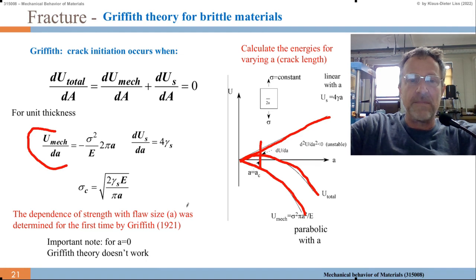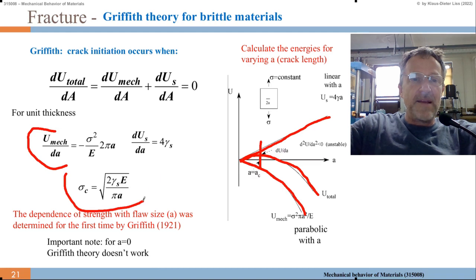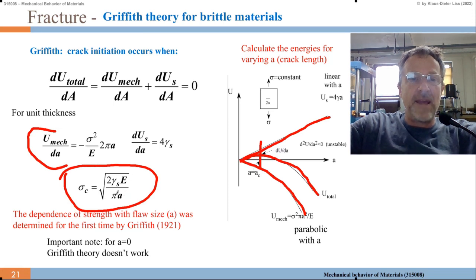And that gives me then a critical stress, or critical A, equals the square root of 2 gamma S E divided by pi A. You can solve it for A with a given applied stress, or with a given A, you can vary the stress and get critical values for both of them.